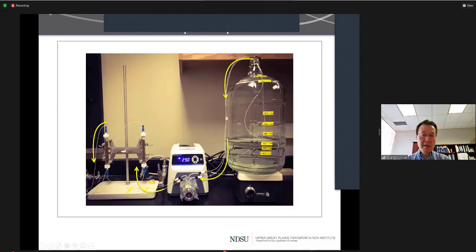So after the batch study, we identified steel chips as the most efficient E. coli adsorbing material, followed by steel slag. So therefore, we decided to perform an additional column study to evaluate the removal efficiency of steel chips under continuous flow conditions, because the column experiment conditions are closer to the real stormwater filter treatment conditions as we continue to push the water through the filter medium.